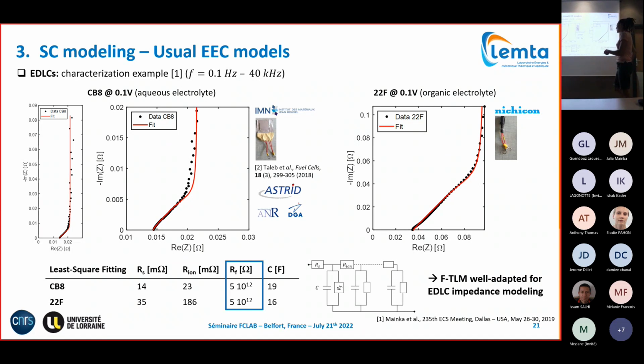In both cases, you see the typical shape of EDLC supercapacitors, and you see in red our fitting curves obtained with our Faradaic TLM. You see a very nice correspondence to the experimental data. Here on the upper part and the lower part, you see the identified parameters. If you have a look, our capacitances and series resistance correspond more or less to what we measured in the time domain. So our parameters corresponded well to what we measured in the time domain.